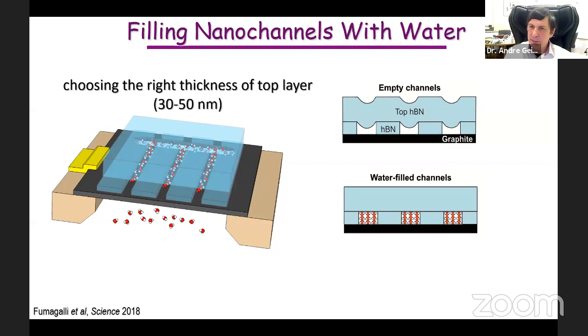So, for example, if you take molybdenum disulfide channels and put deuterium inside, we don't have enough accuracy for this one. But for graphite channels, you can really see that deuterium goes slower than hydrogen, and we attribute this to the de Broglie wavelength, which is of the order of half angstrom, if I remember correctly, is shorter, therefore like light.